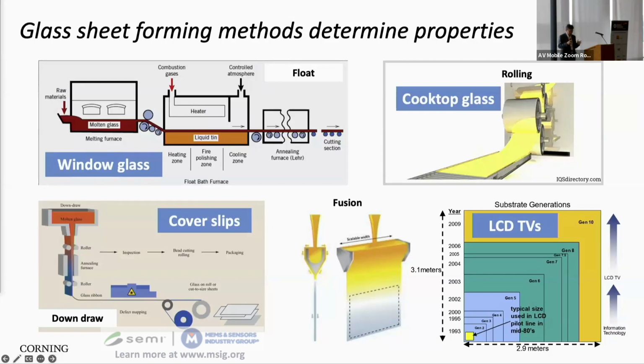And if you look at the cross-section, it's an overflow system where the glass overflows a trough, and then the glass recombines at the bottom of the trough. So the outer surface of the glass sheet has never been in contact with another material. So you get pristine surfaces with very good thickness uniformity. And we can make this now really, really big.